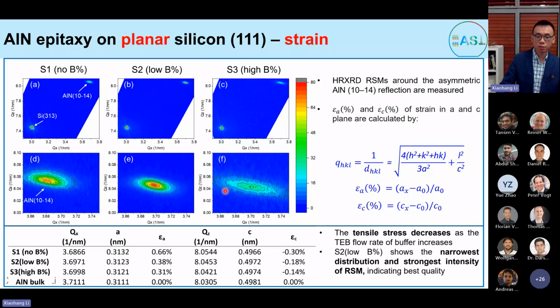So here we have the RSM data, reciprocal space mapping. As you can see here, these are the 3 samples. From here, you can see that sample 2 has the strongest intensity, indicating the highest quality. Also, based on the position of their peaks, we can estimate the remaining tensile strain. We found that the tensile strain does decrease when you increase the boron flow, but sample 3 has the poorest quality. So although it has the lowest strain, the quality is greatly sacrificed.